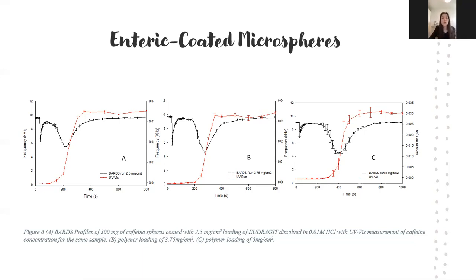So once the coating is fully dissolved at the end of that lag time, there is a rapid increase in the concentration of caffeine. And this causes the end of our lag time and a decrease in the BARDS spectrogram. So the lag time increases as our coating load increases. So that's from A to C, the lag time length increases.